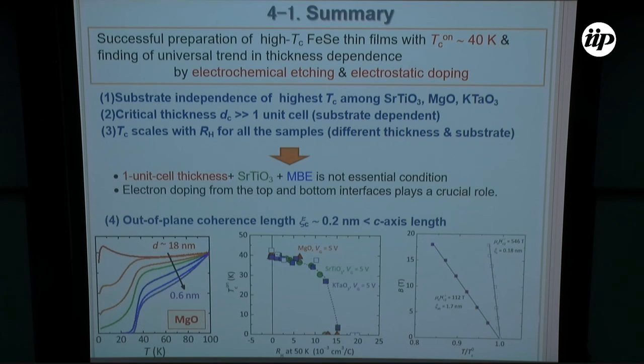Okay, let's summarize my talk. In this work, we successfully prepared high temperature superconductivity with a 40 Kelvin TC by electrochemical etching and electrostatic doping. We found the substrate independence, a critical thickness larger than the one unit cell, and TC scaling with the Hall coefficient. These results indicated that the one unit cell and strontium titanate are not essential conditions, and electron doping from the top or bottom plays a very important, crucial role. We also found the out-of-plane coherence length is very small, smaller than the c-axis length.